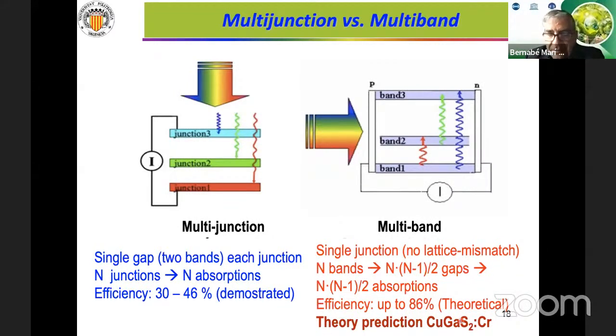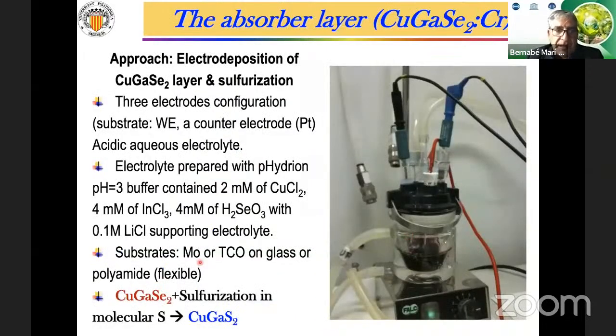The theory predicts that this material, copper gallium sulfide doped with chromium, can be very useful for that. So we have worked on this approach by producing this material, copper gallium sulfide, by means of electrodeposition. Electrodeposition is a cheap technique, very convenient for labs with a limited budget.